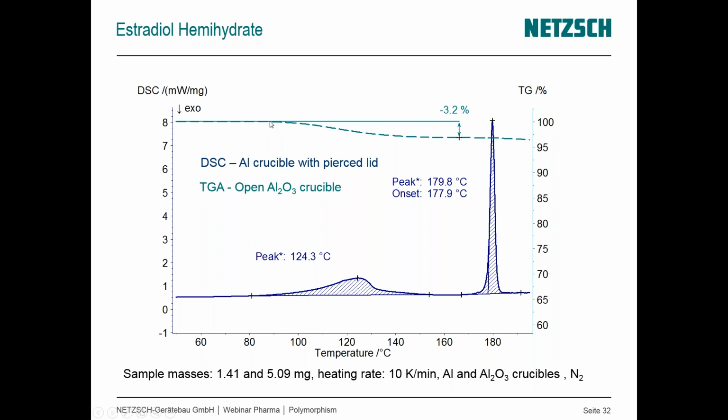we've been looking at these solid-solid transitions so long, you might be in the mode to think this is a solid-solid transition, when in fact, what we have is a solid to gas transition. So this might be solid going to liquid, liquid converting to gas. So that hemihydrate, that water that's bound in the crystal lattice, is being released from the crystal lattice and evaporating.